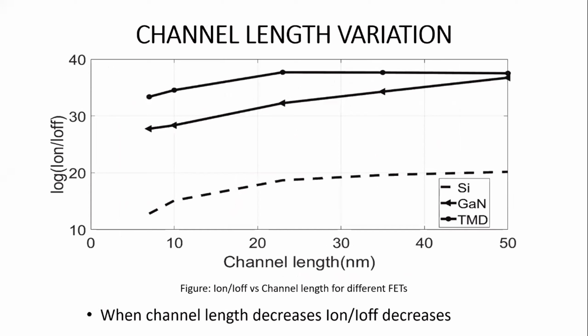Now, here is the channel length variation. In this figure, the Ion/Ioff ratio is increasing from 7 nanometer to 23 nanometer of channel length, but when the channel length is further increased, the Ion/Ioff ratio is nearly unchanged. The reason is that when the channel length is smaller, the change in drain current is significant, because a small change in channel length results in a significant change in carrier density. But for greater channel length, the number of carriers does not increase proportionately. The number of carriers is structured for the current to flow. That is why the Ion/Ioff ratio doesn't increase that much at higher channel length.